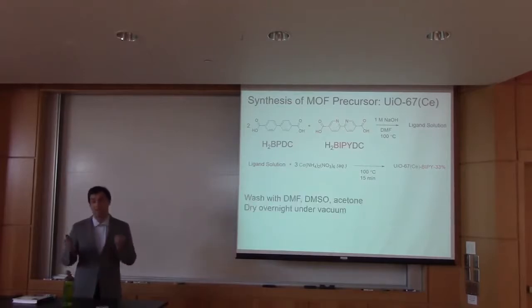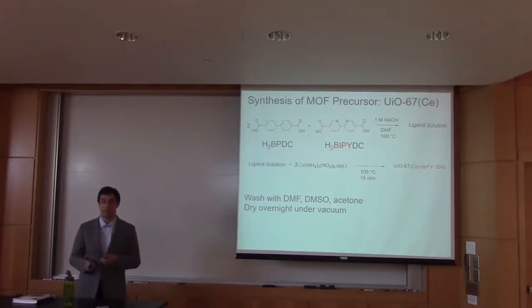Now we have our MOF. We just need to wash it with these organic solvents to remove anything in those large pores, remove any of the starting material, and then we dry overnight to vacate those pores and be left with a solid. It's this kind of pale yellow powder, and this is a very easy step, very repeatable, very nice.